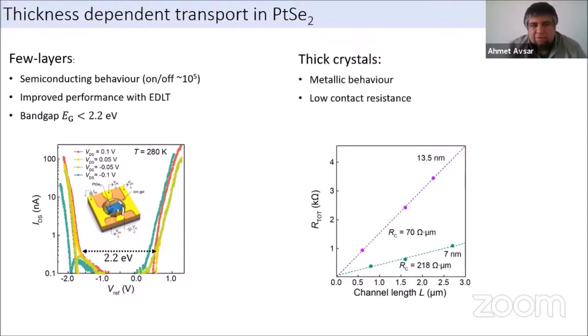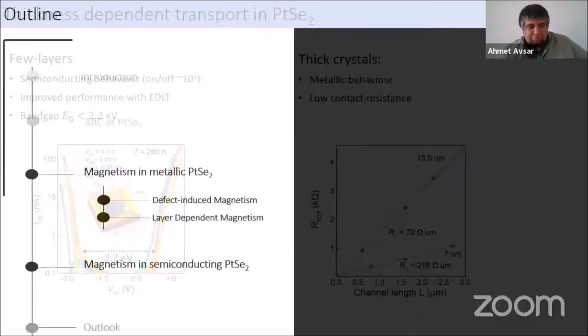Another interesting thing about PtSe2 (platinum diselenide) is that the material shows a very low contact resistance. Compared to other 2D materials, the material is extremely conductive, and it also suggests that this material itself can be used as a contact material to other semiconductors based on 2D materials.